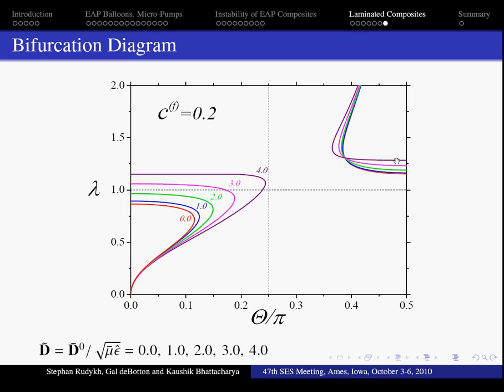Here, the increase of electric excitation results in a stabilization effect. And in this region, the increase of electric excitation opens new angles for the instability. So, either we want to use instability phenomenon for activation or we look for ways to avoid it, we can use this map in manufacturing actuators.